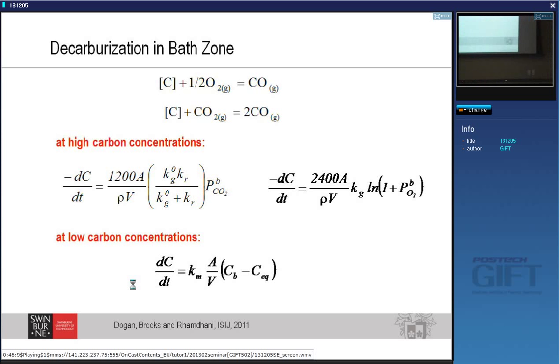In the bath zone, we had to model both the decarburization by oxygen and the decarburization by carbon dioxide. These are two of the mechanisms that we know affect the decarburization. And these equations were established in laboratories, and we also know that at low concentrations this equation governs the decarburization behavior.